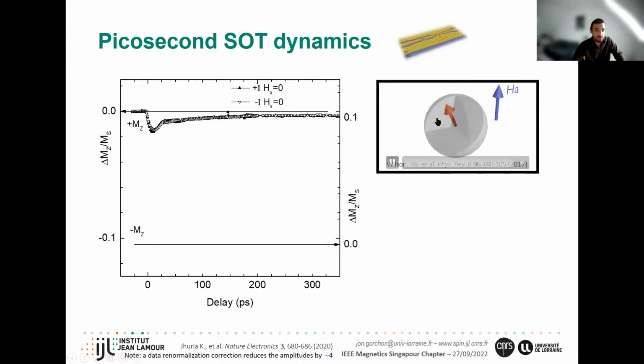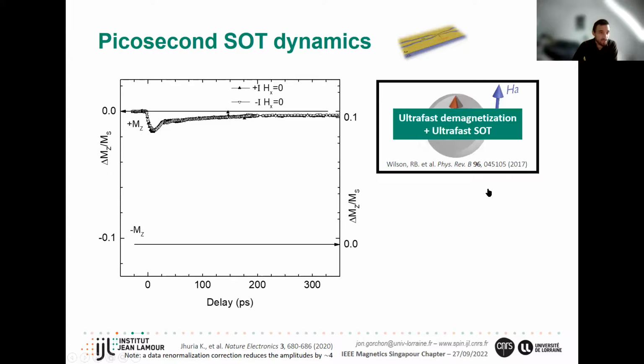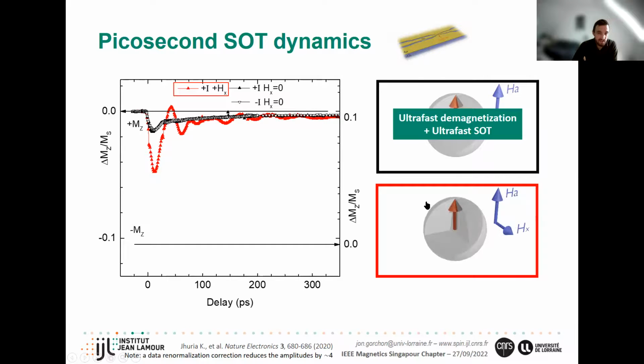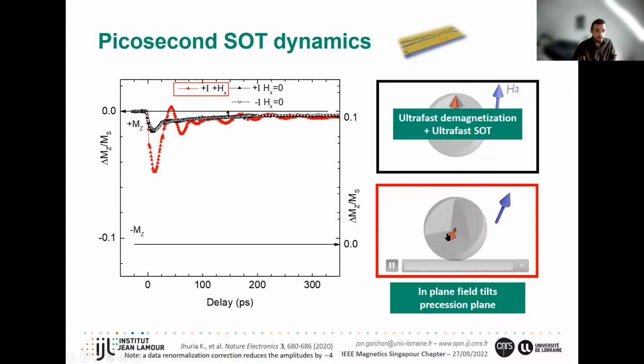And so this spin is going to torque the magnetization, and then the magnetization is going to precess around the equilibrium field. In this case, any precession plane is in the plane of the sample, and we are only sensitive to Z. So what we do is add a little in-plane field and tilt the magnetization. We add this HX field, which means that now the effective field is tilted. So this is the initial point where we're going to excite the magnet. We torque it, so it goes away from equilibrium, and now it's going to precess around this tilted effective field. And so there's a little out-of-plane component that's going to oscillate, and we're going to see it. So this is what is going on here.